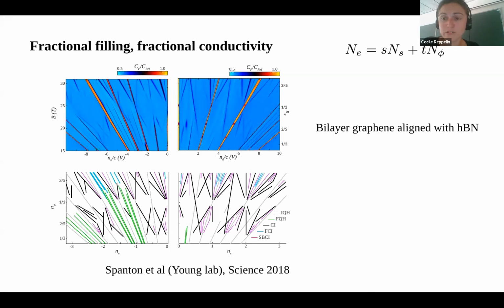So the origin of the moire superlattice is, again, like the previous data I showed, due to the lattice constant mismatch between graphene and HBN. And again, this is data in the B magnetic field versus electronic density plane. Here, this is not actually conductance data, but capacitance. This is a different way of probing whether your system is compressible or not. But again, you have these different lines, which have been analyzed by the authors in this